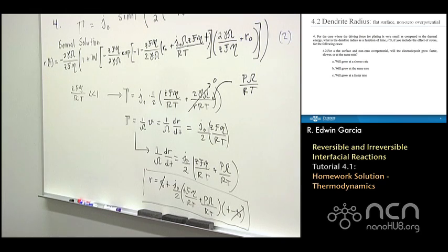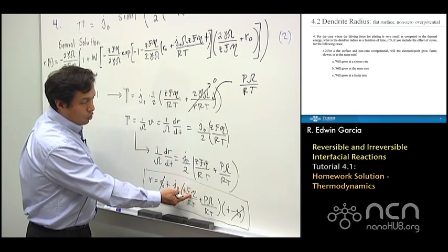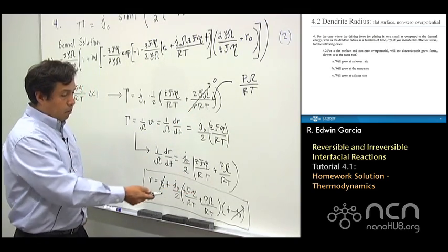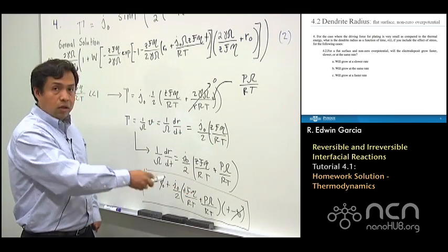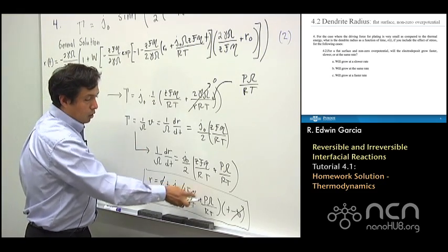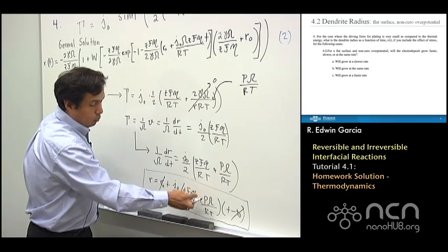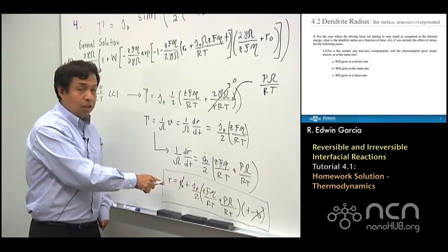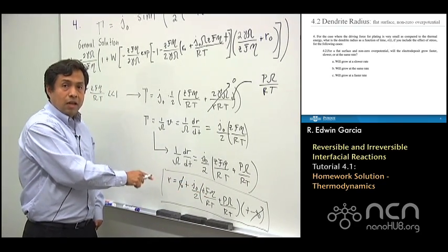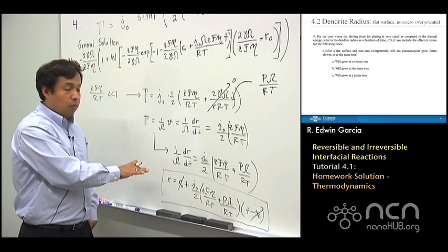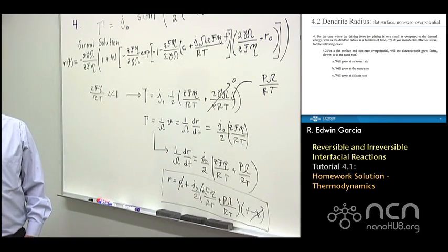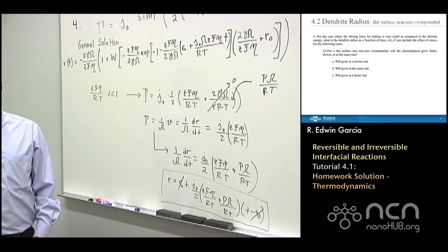In this case, since we have a non-zero overpotential on a flat surface, which corresponds to this situation, the pressure is suppressing the growth rate. We can say that the dendrite will be growing much slower than if there is no pressure. So that makes answer A the correct answer.